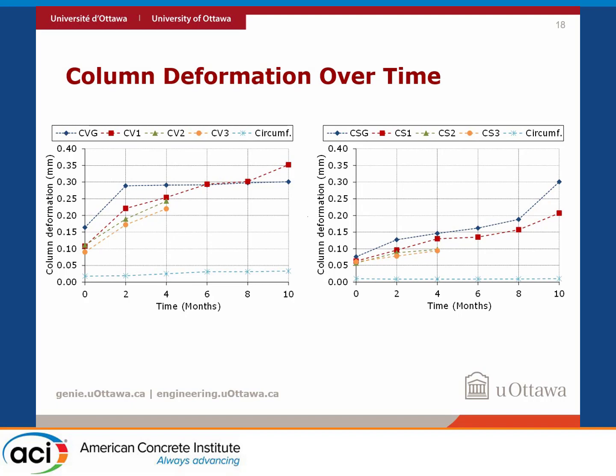Column deformation over time is actually similar in both types of columns. It's just the rate of increase of that deformation over time that differs. So when we look at the specimens with the longitudinal reinforcement being corroded, the rate of increase of deformation is greater at the beginning, whereas for the other types of columns, it tends to increase at the beginning for the first 2 months, then it stabilizes, and it increases again after a period of time.